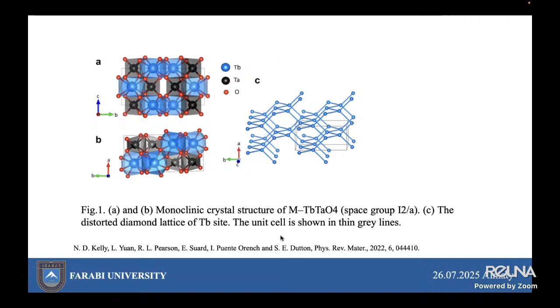And on this picture, you see that the polycrystalline terbium tantalate was synthesized according to the solid state ceramic reaction. The powder was firstly heated at 800 Celsius overnight to remove moisture. Of course, at the Cavendish Laboratory, we used powder X-ray diffraction, which was carried out at room temperature on the Bruker diffractometer, and we also carried out Rietveld refinements using the Topas program with the Chebyshev polynomial background and the Thompson-Cox-Hastings pseudo-Voigt peak shape.